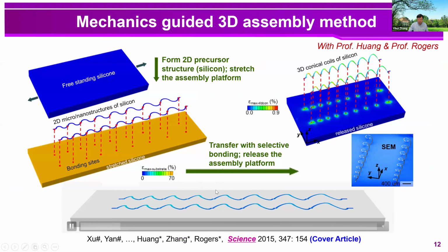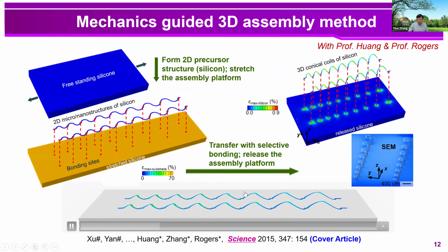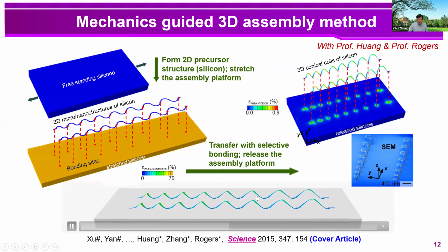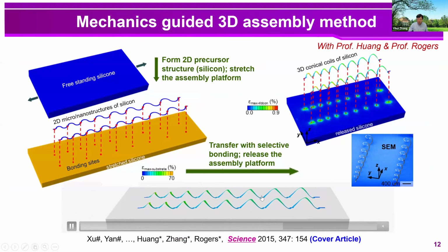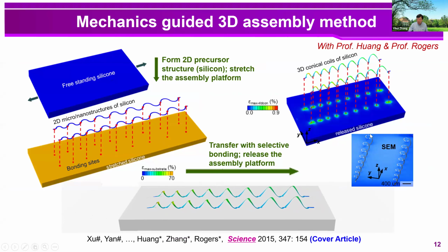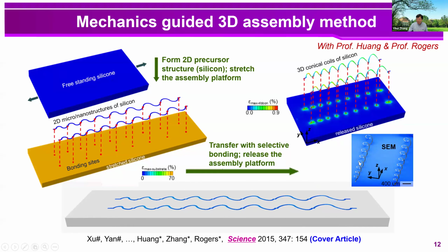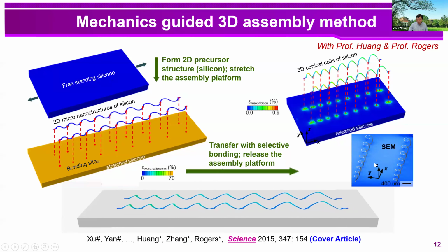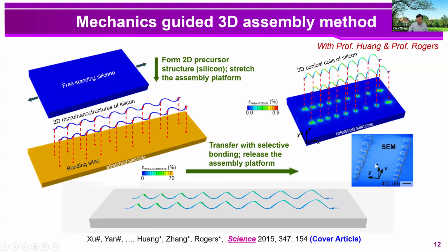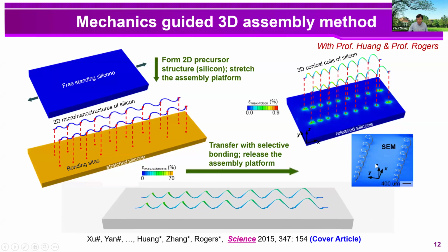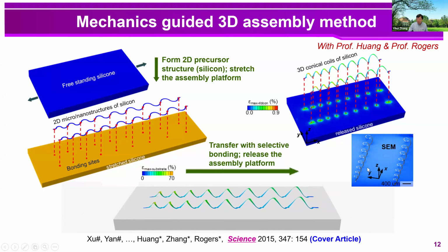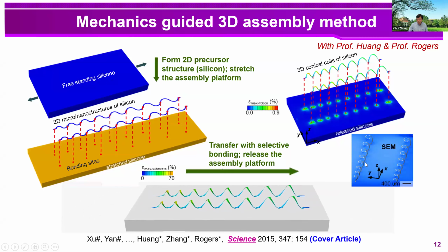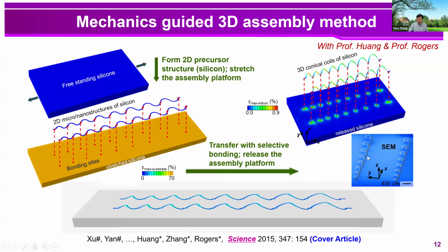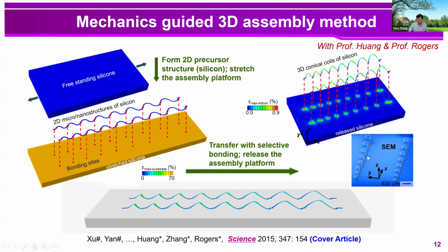So in this example, the 2D serpentine deforms into a 3D conical coil after release of the pre-strain. This idea has been validated by our experiments. If you look at the SEM image here, this is actually the experimental result done in 2013. This material is made of single crystal silicon, the most important material in the information industries.